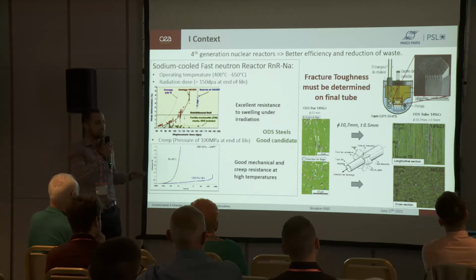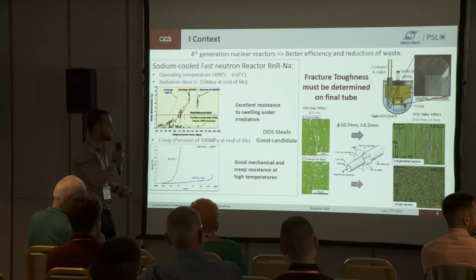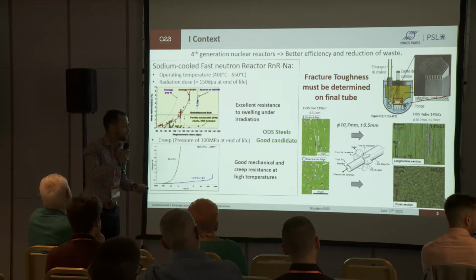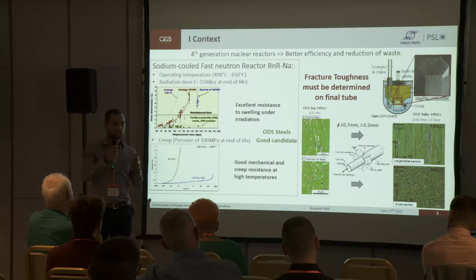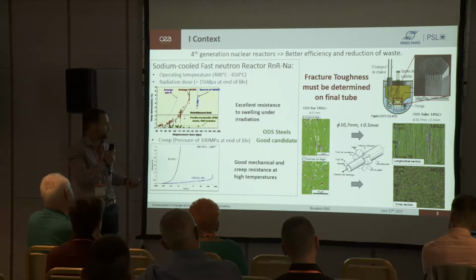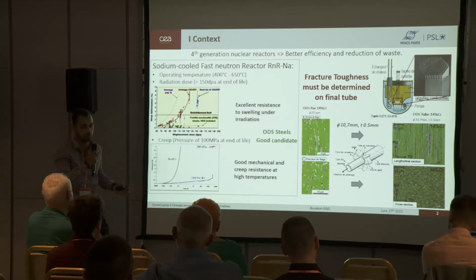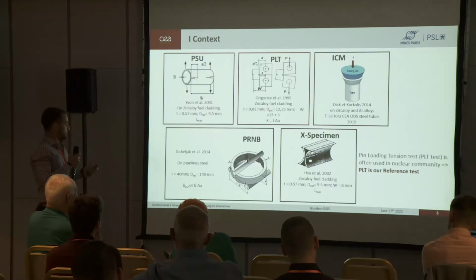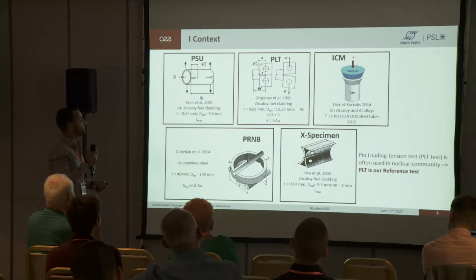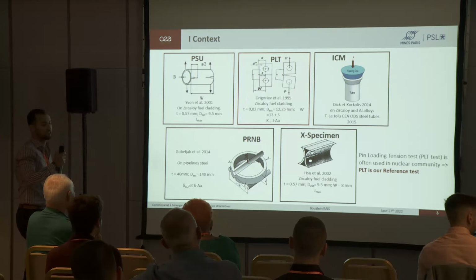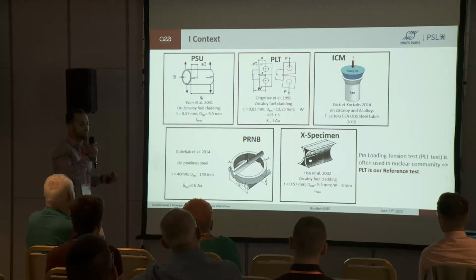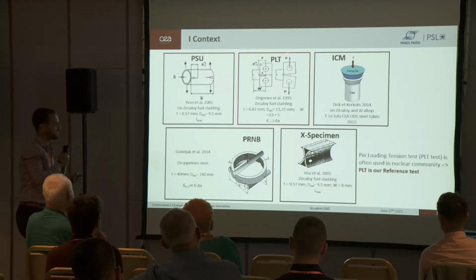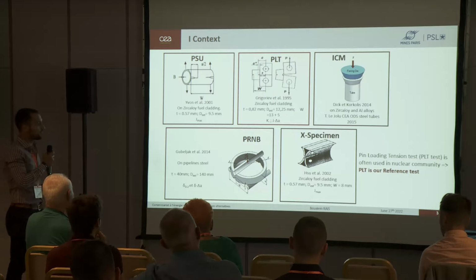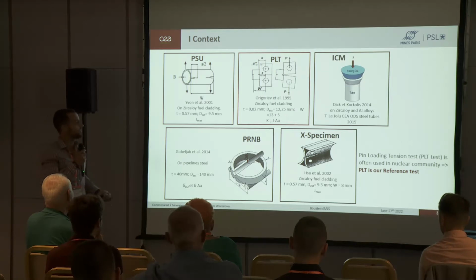So it is necessary to assess the toughness of this material in its final geometry. However, because of their small size, we can't sample standard specimens from these tubes. So the principal objective of my thesis is to develop an experimental procedure to assess the fracture toughness of thin wall tubes, or of fuel claddings. To reach this objective, some tests are proposed in the literature to assess the fracture toughness of specimens extracted from tubes. The PLT test, for pin loading tension test, here in the red border, is often used in the nuclear community and will be our reference test.